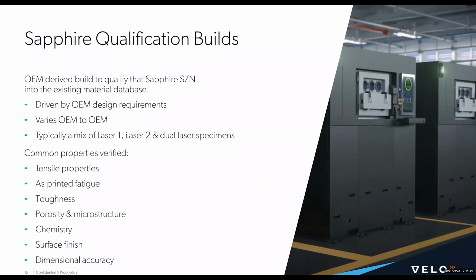Typically, these are a mix of laser 1, laser 2, and dual laser specimens. And here is a list of what we commonly see with these. Tensile properties are basically always there. Oftentimes, designs are limited by fatigue, and so fatigue is often verified. Toughness comes up as well. And then generally, there's always a process cube in there for verifying lack of porosity, microstructure, chemistry, surface finish, and dimensional accuracy. This is a little redundant with the site acceptance test build, but many OEMs want that level of consistency, where they're tracking it on their Sapphire qualification build reports as well.